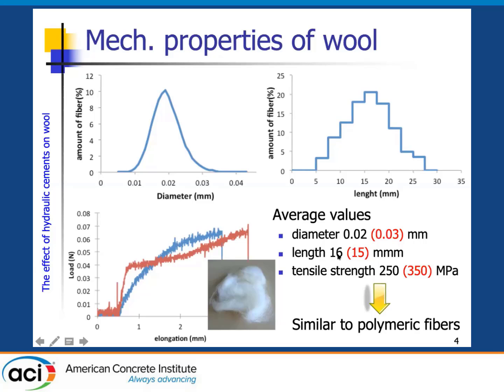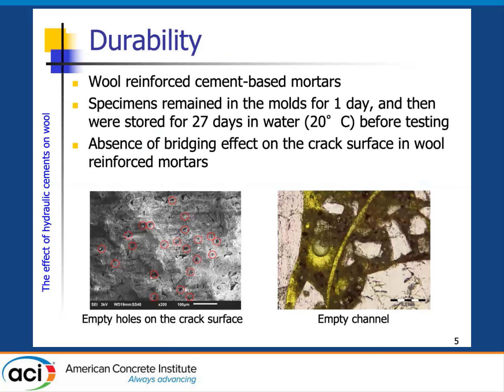And also the length, in this case the average length, is 16 millimeter for wool and 15 for plastic fibers, and the strength 250 megapascal for wool and 350 for polypropylene fibers. So the red values and the black ones are similar. The wool filaments are quite similar to the polypropylene fibers. So it can be used to reinforce concrete or cement-based mortars. However, we have a problem because if we cast fiber reinforced mortars by using wool,